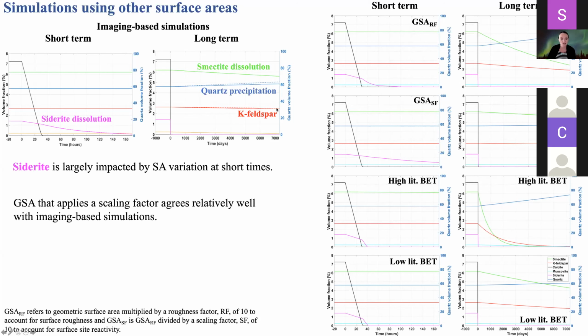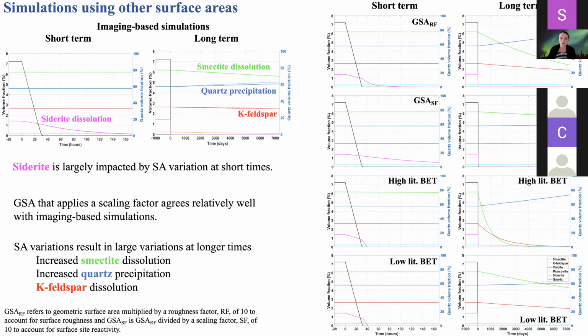And then in terms of the other mineral phases, at short times, we don't really have anything happening, but over longer time scales, you can see the evolution of minerals does vary widely, where you have increased smectite dissolution with larger surface areas, increased quartz precipitation, and then some simulations also show consumption of potassium feldspar. And so you can get really different results in the evolution of mineralogy depending on the surface area that you're using.